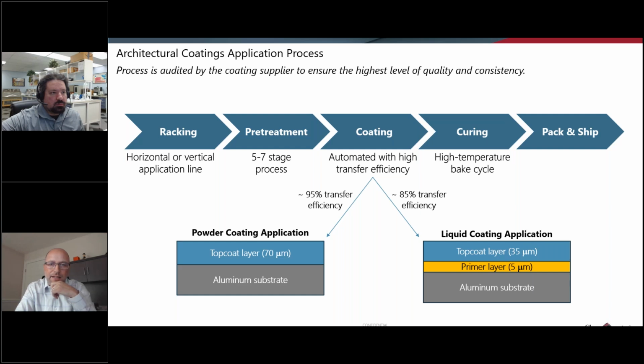What I mean by that is you're going to have either a horizontal or vertical line, and I'll talk a little bit about that in a minute. If it's a horizontal line, you're going to have people actually hanging parts on hooks on a conveyor belt so that they can go through this process. Once that happens, the conveyor is going to take it through a pre-treatment process, which is usually a 5 to 7 stage process to make sure that you're going to get all of the adhesion and the corrosion resistance that you need out of your coatings.